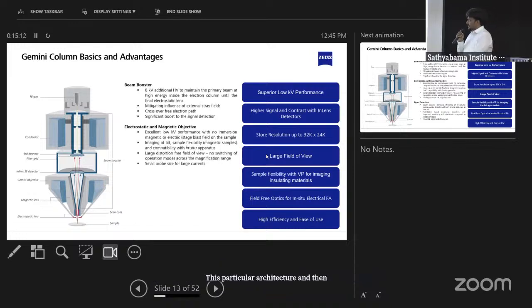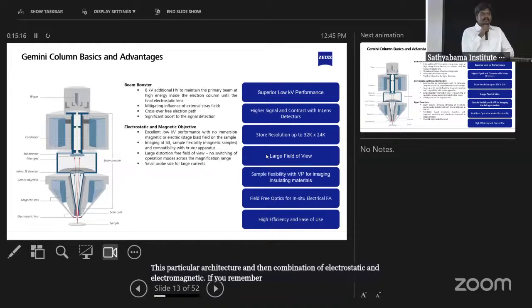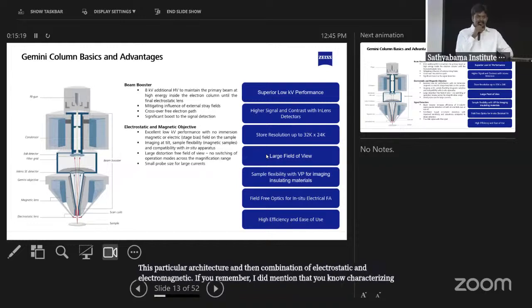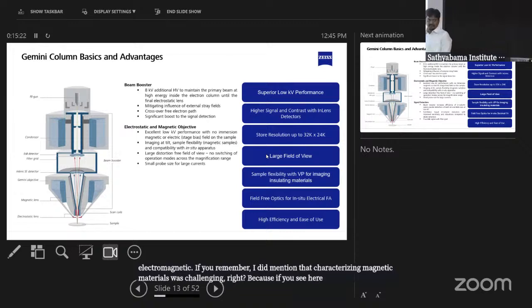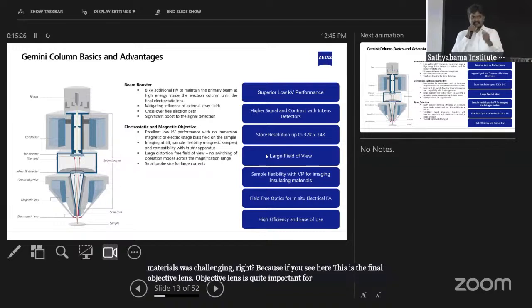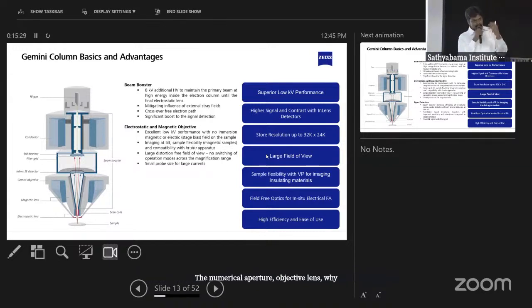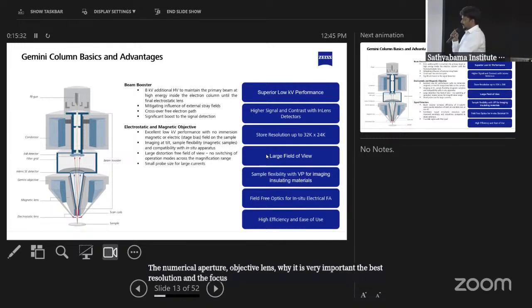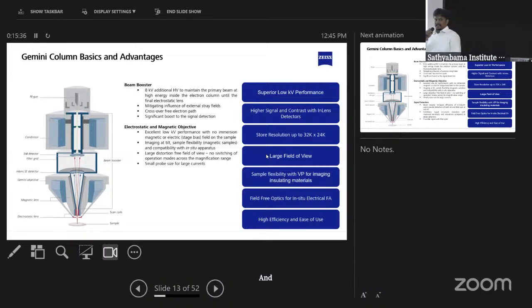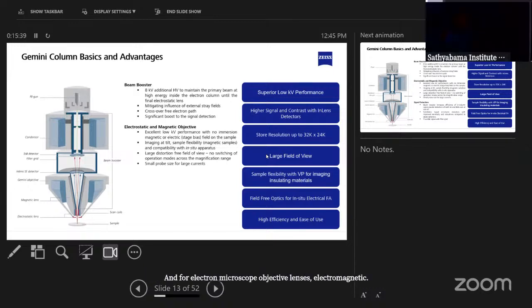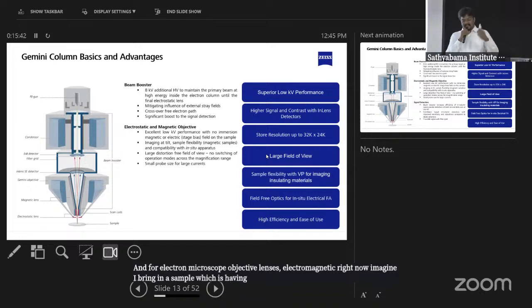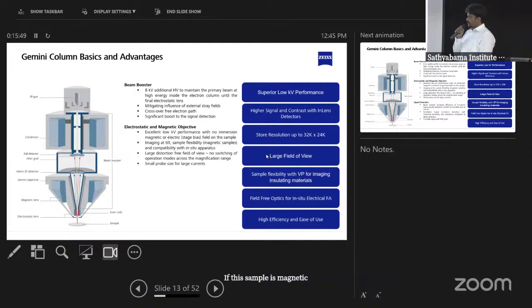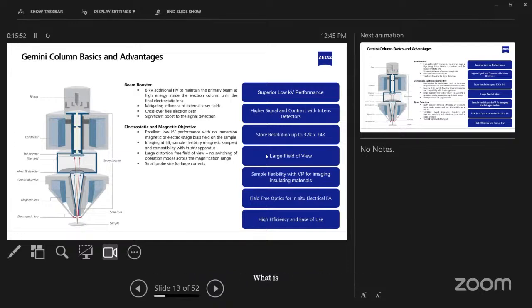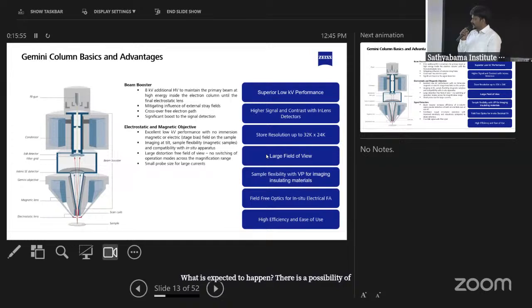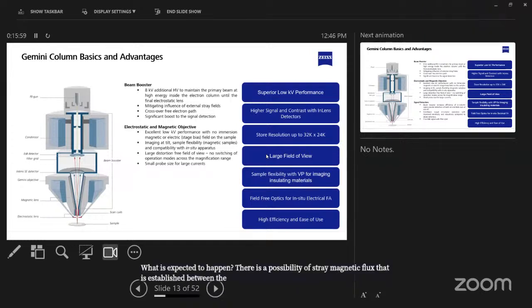And then the combination of electrostatic and electromagnetic. If you remember, I did mention that characterizing magnetic materials was challenging, right? Because if you see here, this is the final objective lens. The objective lens is quite important for any microscope, right? We all understand the numerical aperture, and why the objective lens is very important. The best resolution and the focus point are all by the influence of the objective lens. And for an electron microscope, the objective lens is electromagnetic, right? Now imagine I bring in a sample which is a strongly magnetic material, or even a rare earth magnetic material. If this sample is magnetic, when I try to bring it close to the objective lens, what is expected to happen? There is a possibility of stray magnetic flux that is established between the objective lens and the sample, right?